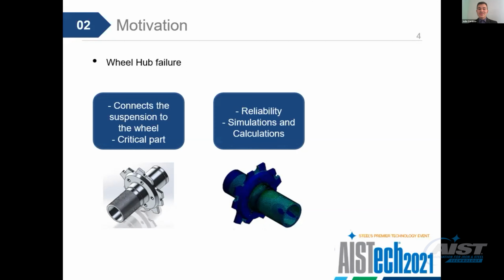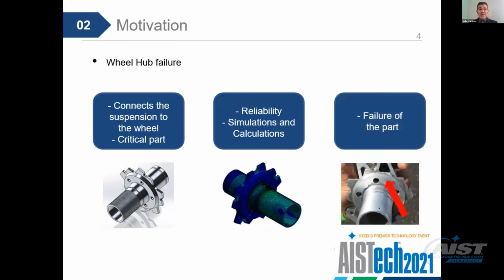So we carried out structural, fatigue, and dynamic simulations of both the separated part as well as the whole suspension system. But despite all the calculations, the front wheel hub broke during a test much earlier than we were expecting. And this fact motivated the team to investigate the failure.